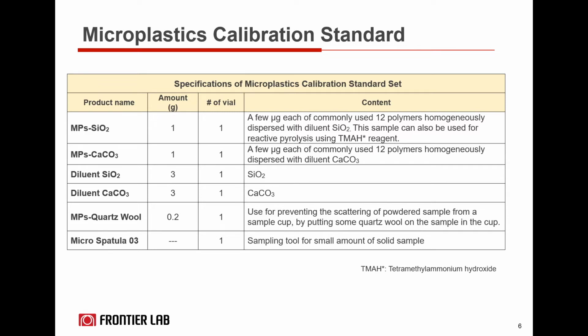Two microplastic calibration standards with different diluents, SiO2 or CaCO3, are available as part of the set for you. Both samples contain a few micrograms each of 12 commonly used polymers, which are homogeneously dispersed with a solid diluent for easy weighing on a semi-microbalance. In addition, as I mentioned, as part of the calibration set, you also have the diluents SiO2 and CaCO3 that you can use for preparing your own standard samples. And this table here shows pretty much the content of your microplastic calibration standard set.